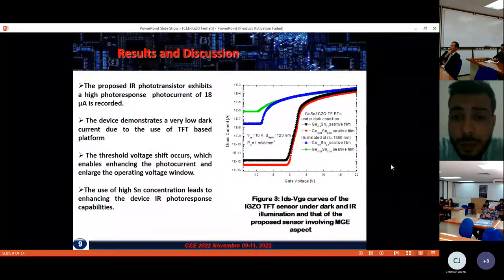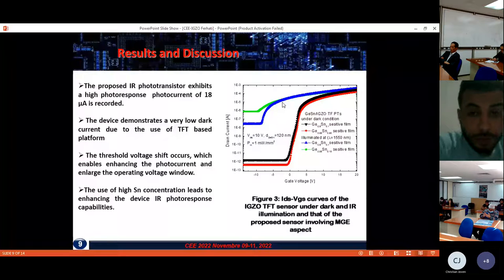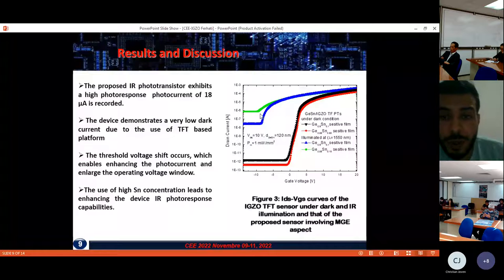In order to assess the performance of the device, we can see from this figure, which describes the drain current as a function of the gate voltage under dark and infrared illumination conditions. It can be seen from this figure that the proposed infrared phototransistor shows high photoresponse characteristics in the negative voltages as compared to the conventional one, which cannot respond in the infrared region.